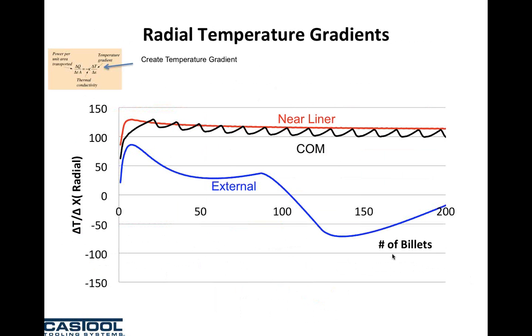If you have an externally heated container, you see on the x-axis is the number of billets from 0 to 200 billets. You see you have a temperature swing from positive gradient to negative gradient. That means sometimes your container is actually providing more heat than you needed to your liner. So your liner temperature is not stable at all. It can be hotter than your billet, or colder than your billet at random. And when it's hotter, you're going to get type A inflow.